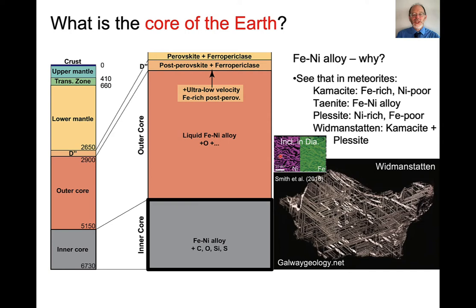In my previous lecture, I mentioned that this is something that we see as inclusions in diamonds now. The relatively recent discovery where we see a nickel rich metal and iron rich metal composite inclusions inside diamonds, but it's also what we see in meteorites. There is a metal alloy called taenite, which is an iron nickel alloy, but there are meteorites that contain taenite, which is an iron nickel alloy that we think is representative of what we might see in the Earth's core. This alloy is not stable if it cools slowly and instead separates into an iron rich nickel poor mineral that's called kamacite and a nickel rich iron poor metal that we call plessite. There's an interesting pattern. It's called a Widmanstätten pattern, which is an intergrowth of kamacite and plessite. This is an example of the Widmanstätten pattern in a meteorite.